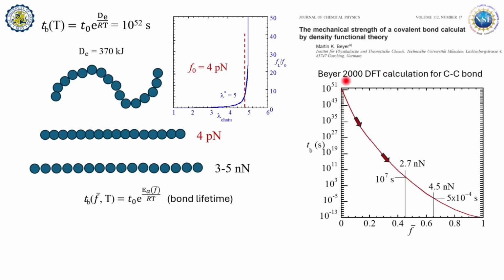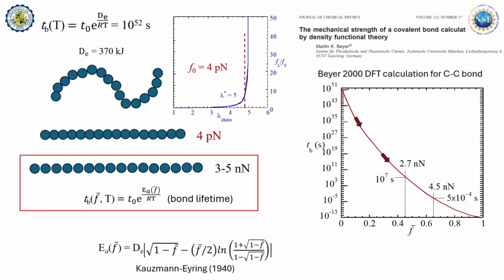According to this, I would call it a celebrated result of DFT calculations, the lifetime of the bond crashes. Look at the interesting region I labeled. It can go to 1/10 of a millisecond within this narrow range of the tension in the bond. And all that is actually analytically described early on. In other words, this activation barrier that you have to overcome is explicitly related to how much tension.